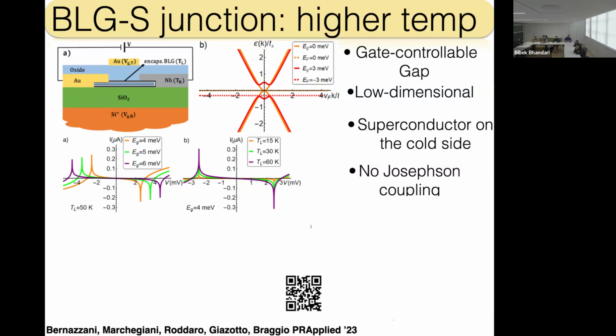Until now, I always discussed a system where they are all superconductor. But at the beginning, I told you one thing. What is really important is the cold side, that you have a density of states that shifts with the energy. But I don't discuss too much the hot side. The only important thing of the hot side is that there is a gap. And if you get a gap, you can do this not with a superconductor, you can do it with a semiconductor. And in this case, for example, we decided to use bilayer graphene.